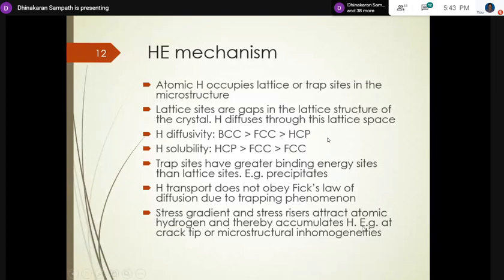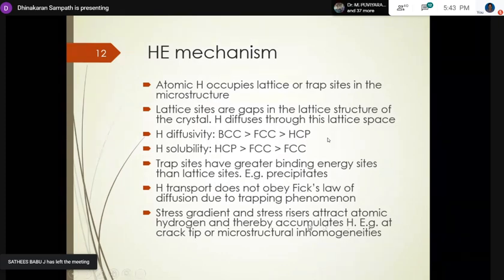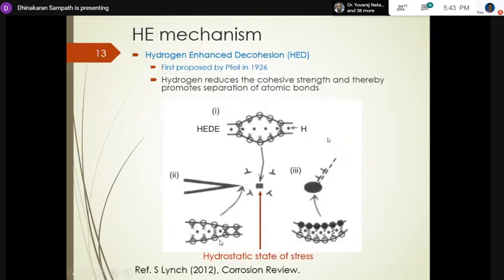And also at cracks, stress gradients in the material, stress risers, also attract hydrogen, thereby accumulating lots and lots of hydrogen. That means at the crack tip, hydrogen accumulates a lot. So we are going to look at some models. They actually explain the mechanism.